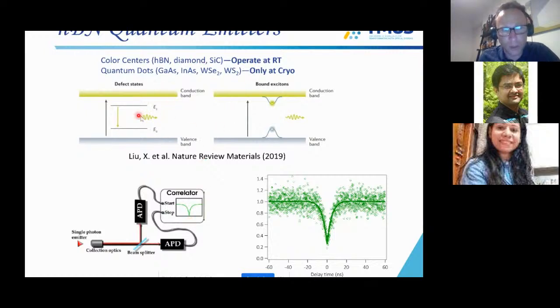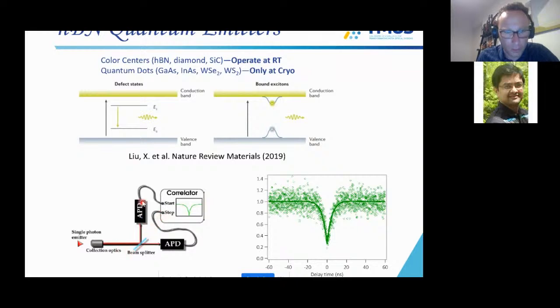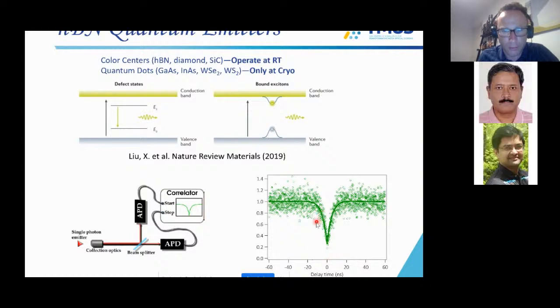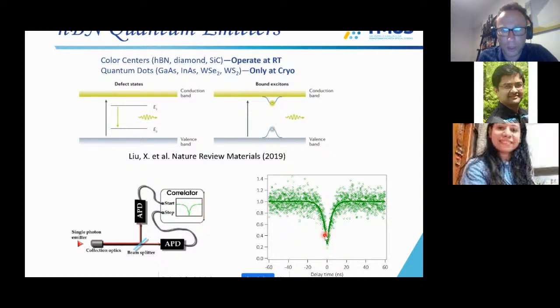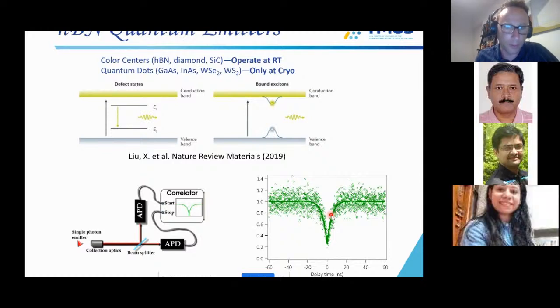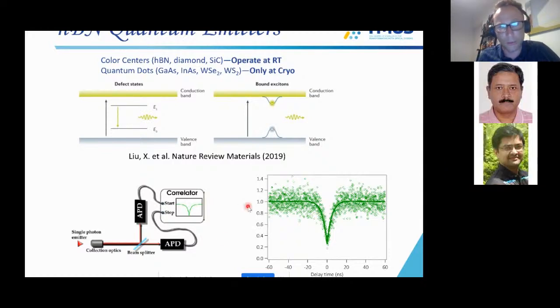And so to know whether you have a single photon source or not, you measure what we call a Hanbury Brown and Twiss measurement, or an HBT, or an anti-bunching curve. You simply split your light between two detectors, and you measure start and stop correlations, and you have a dip here at zero delay time. If you have this missing count rate here, or a dip, that means that you have a single photon source. And so you will see quite a few of those dips, and g2 functions, as we call them, in my talk. So I thought I would just put a slide here to emphasize.